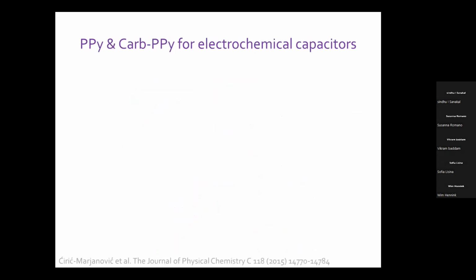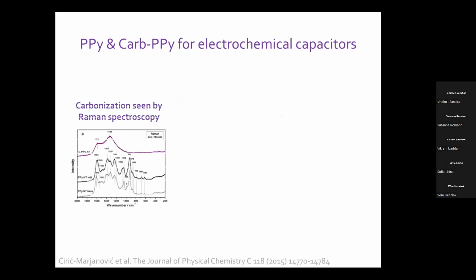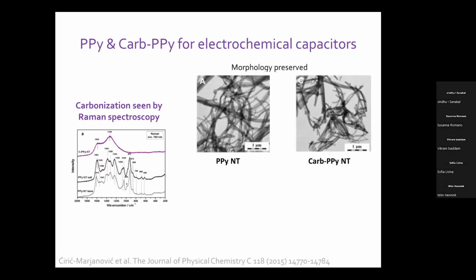We could also show some examples of polypyrrole and carbonized polypyrrole used for electrochemical capacitors. Here we show how polypyrrole is converted to carbon. So there are very prominent changes in the Raman spectra. However, what is really interesting and important is that morphology is preserved. So basically, there are some polypyrrole nanotubes which are converted during the carbonization into carbonized polypyrrole nanotubes.